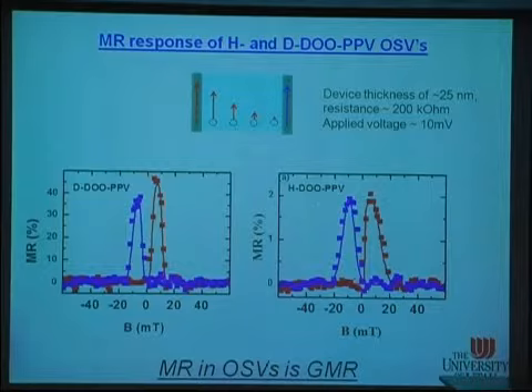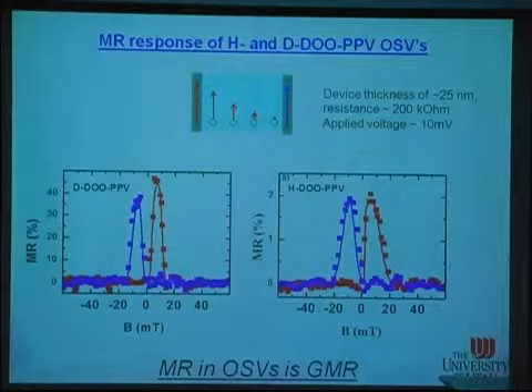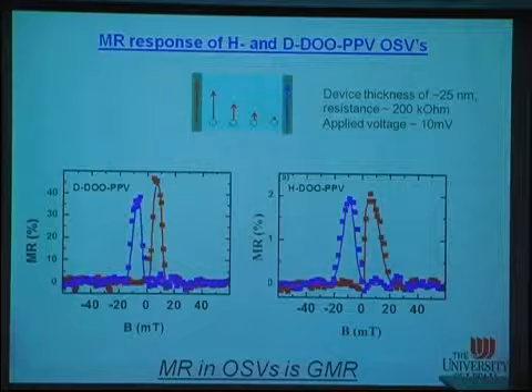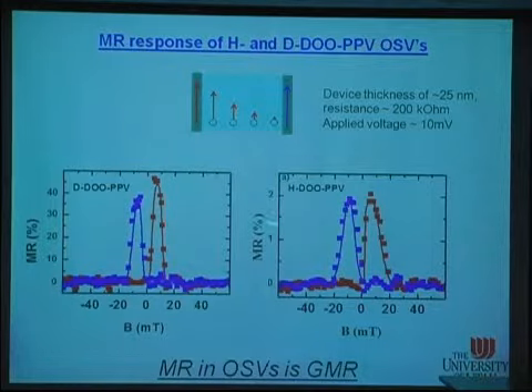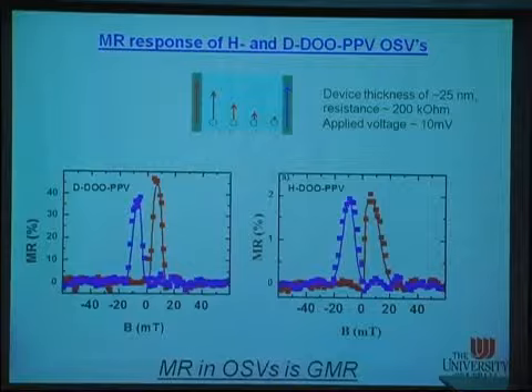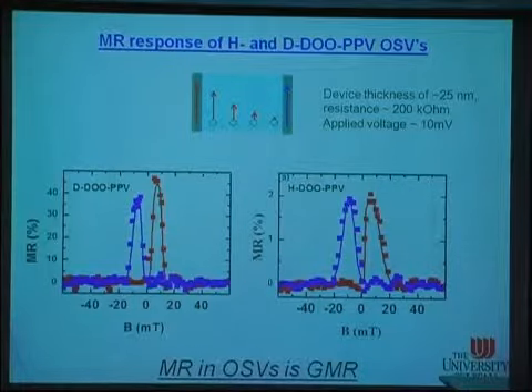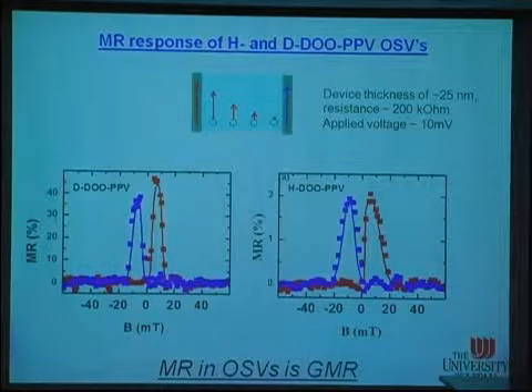What temperature is that? At what temperature? At 10 kelvins. Yeah. So if the effect were really because of the tunneling effect, you would see the same magnetoresistance magnitude here, because tunneling doesn't care if the spacer is deuterated or hydrogenated. So this is the definite proof that we have spin transport inside the materials.